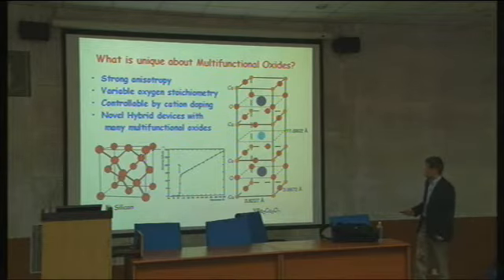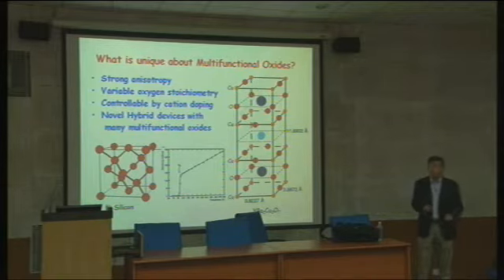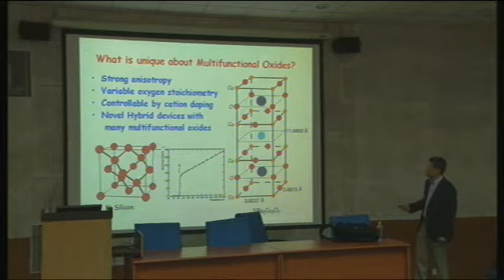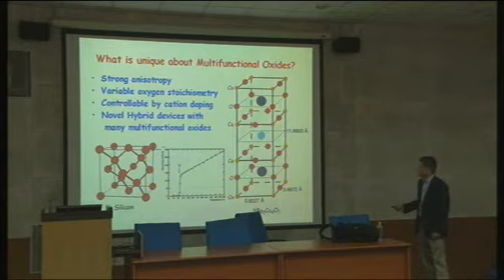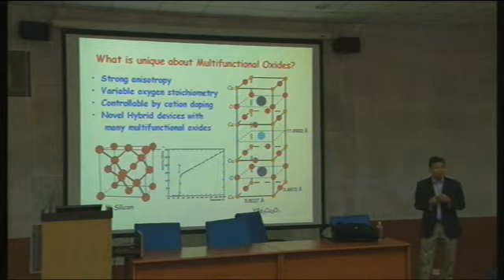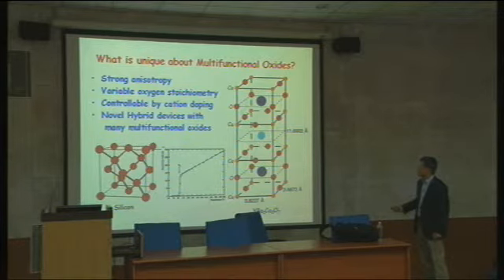Okay? The stoichiometry of these is very important, and this atomic site and here the copper oxygen planes are important for the superconductivity. You have an A site and B site, and also your copper oxygen planes. Another important perspective is that oxygen goes in and out of this system, making yttrium barium copper oxide O7 minus delta, and that takes the material from superconducting to insulating. As you can see from the structural point of view, it is not only very different and complex, this structure is also very anisotropic. The superconducting coherence length, which means how far the superconductivity actually reaches, is much shorter in this direction than in the A and B directions. That's why we call this very strong anisotropy.